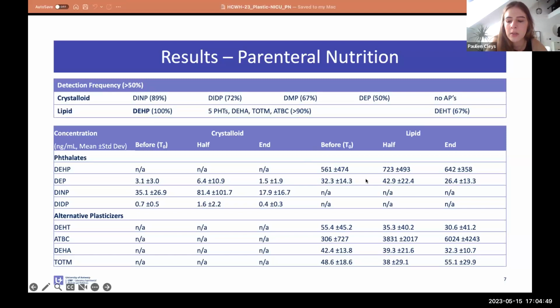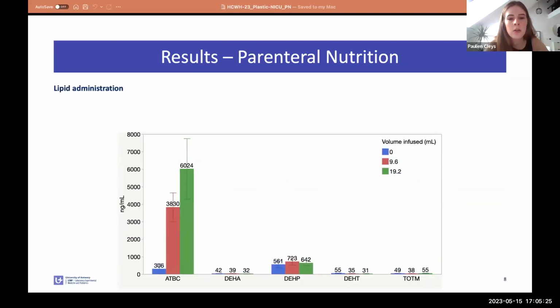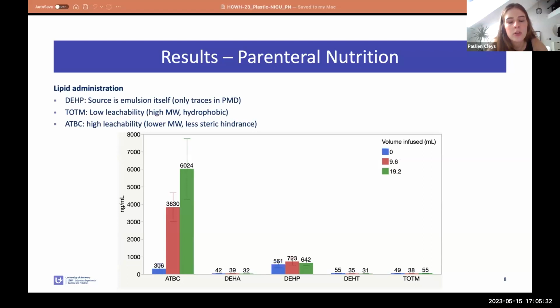In these non-lipid samples, we see DINP and to a smaller extent DIDP, but also with low detection frequencies in the lipid samples. So similarly to the DEHP, we assume that the source of DINP in the non-lipid samples is maybe this infusion solution itself, as we don't see an increase of the concentrations in function of time. And then the leachability patterns or the leachability profiles of the different plasticizers next to each other. So these concentrations show the concentrations in the lipid samples in the beginning of the infusion and at time point 12 hours and 24 hours.